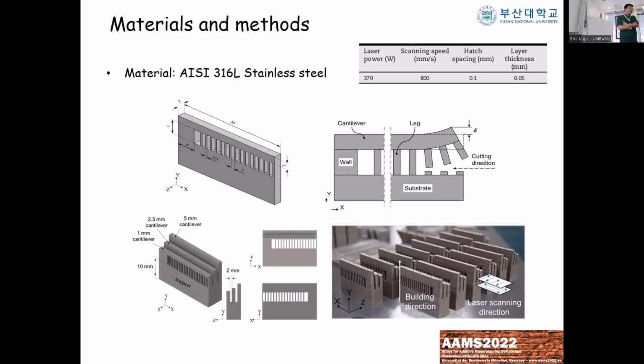To develop the model, or simply to measure the residual stress, we first have to find an efficient way to experimentally measure the residual stress. That's why we designed a special structure, which we call a cantilever, which is quite common in measuring residual stress. So we have a cantilever beam in the above, which is connected with supporter legs. And while we are printing those supporter legs, they are free to move in the lateral direction, so they don't have any residual stress in this direction.